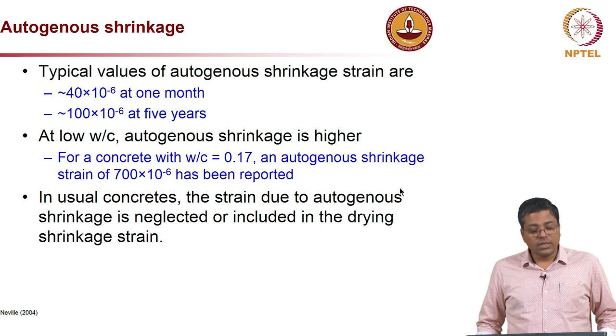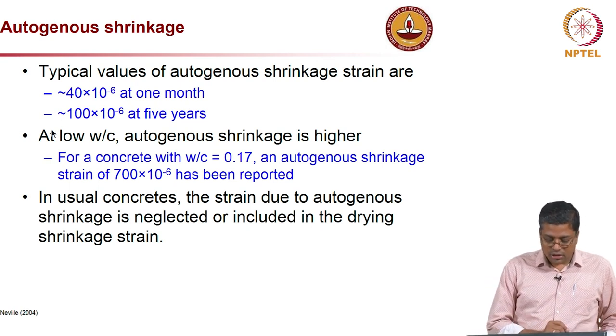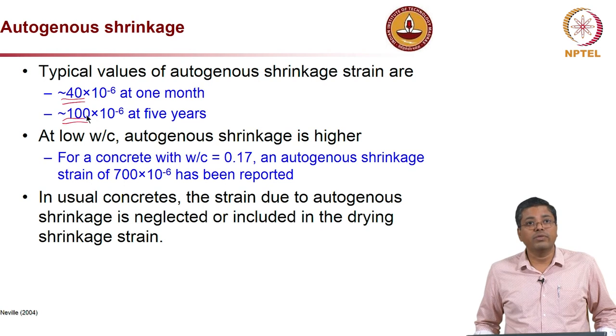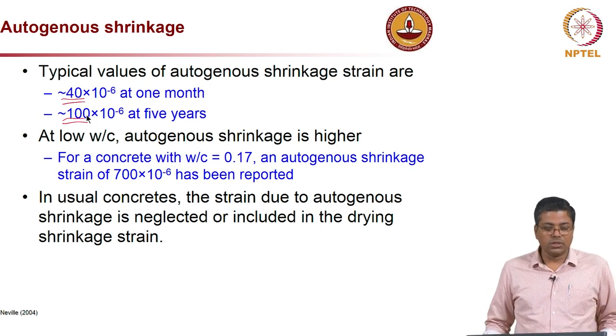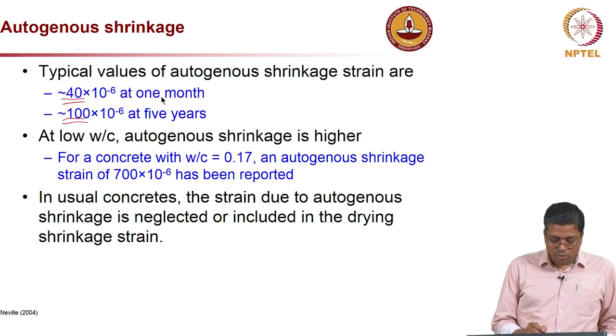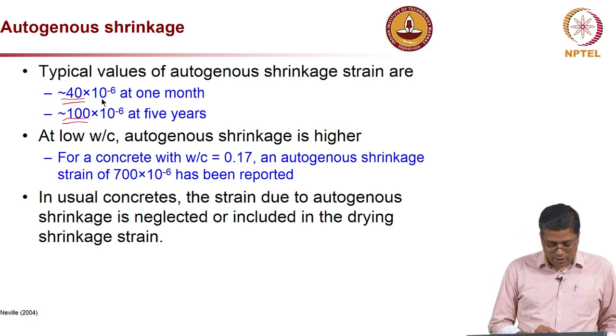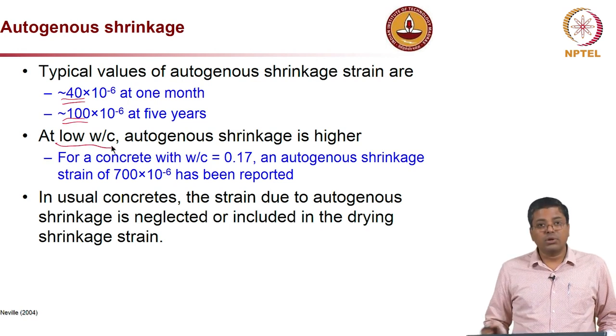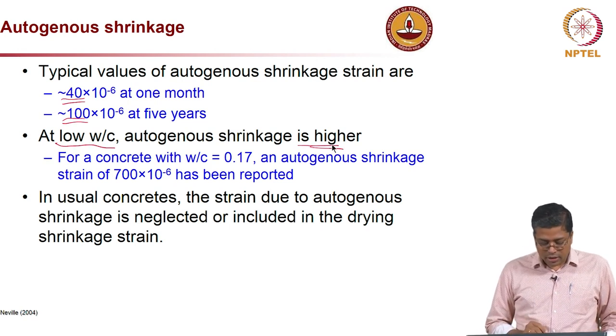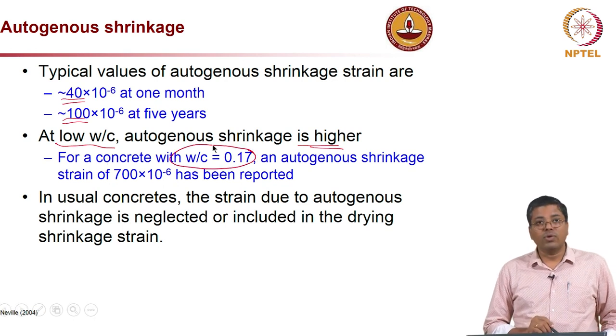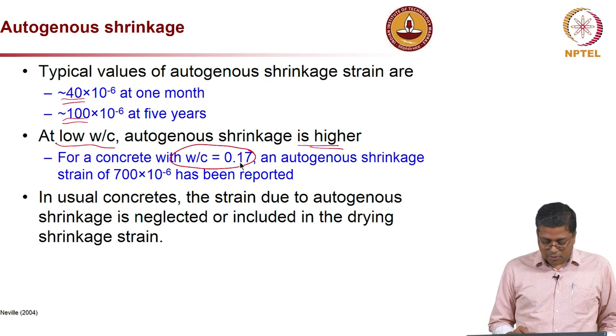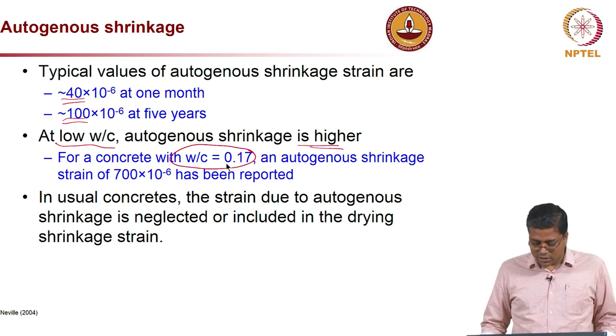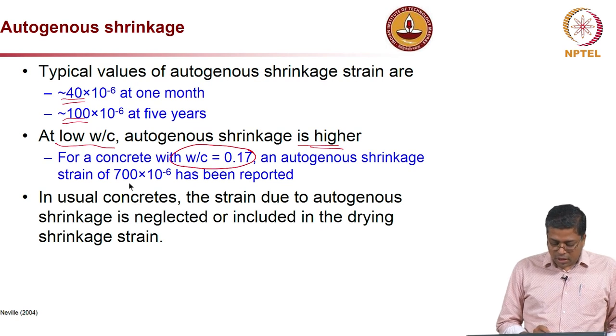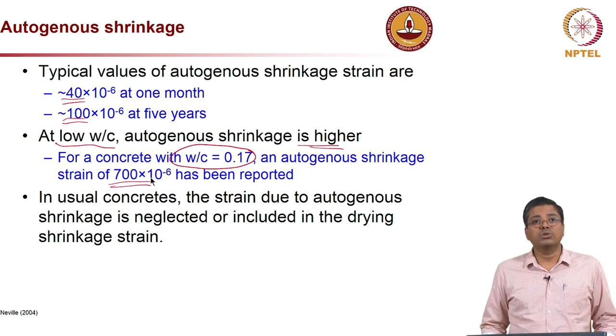Now what are the typical values? If you are talking about autogenous shrinkage strain, it is about 40 microstrain in 1 month and about 100 in 5 years. So most of this is happening in the very beginning, almost 40% is happening in the first month itself. Now if you are talking about a low water cement ratio concrete, autogenous shrinkage is higher. For example, the water cement ratio of 0.17, this is for experimental purpose, because we hardly use 0.17 water cement ratio concrete, but you can see here autogenous shrinkage of 700 microstrain has been reported.